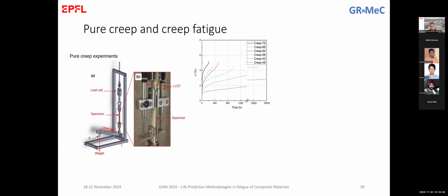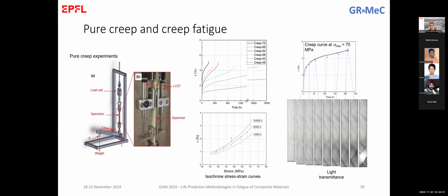You apply a stress level here, and you keep it constant, and you measure the strain with time. And this is what we measure for higher stresses. Of course, you have more rapid strain increase. For lower, you have lower. So this is information that we kept for the next step, to correlate creep and fatigue in the same experimental procedure. We also took some photos during the creep testing to investigate also the damage evolution in creep.